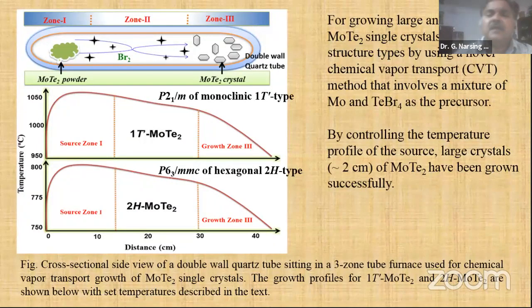By controlling the temperature profiles, these are the profiles of the temperatures. What Purushottam told about the microwave, just press the button and the temperature is set automatically. But here we have to set 3 different zones: the first zone, second zone, and third zone. The second to third zone is very important. The first zone has the source material. You can heat up to 1050, then slowly decrease the temperature, so you can get single crystals in the second to third zone. This is the growth zone.